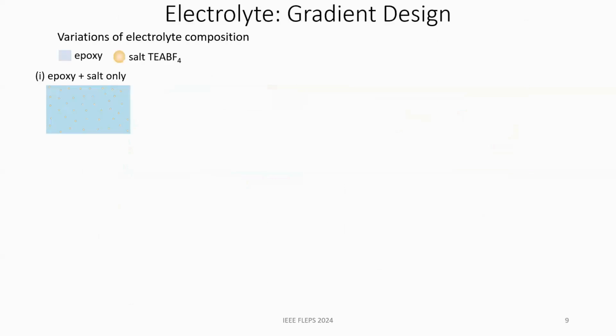Okay, now it's time for the electrolyte. So a typical solid-state electrolyte uses epoxy to bind the separator and the electrodes together, and so that gives it the mechanical strength. And then a conducting salt, we're using TEABF4. So prior works have used this combination, and it ends up blocking the redox sites.